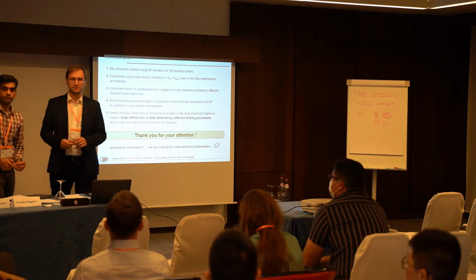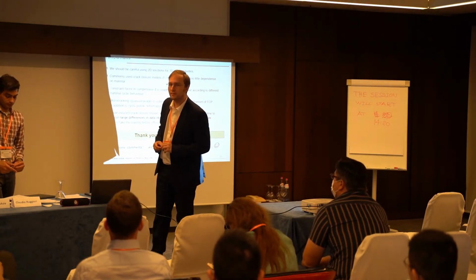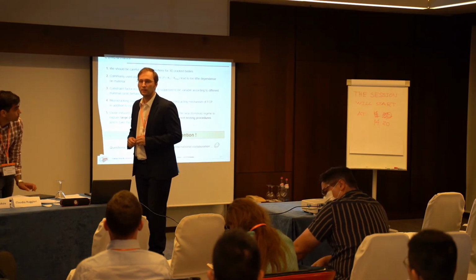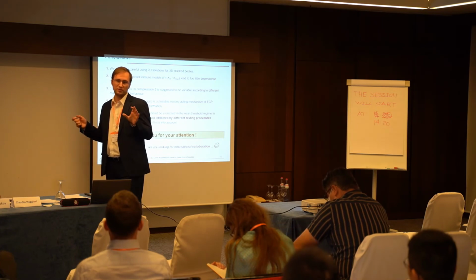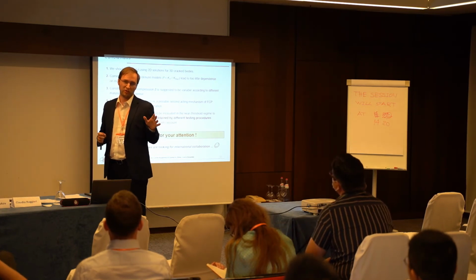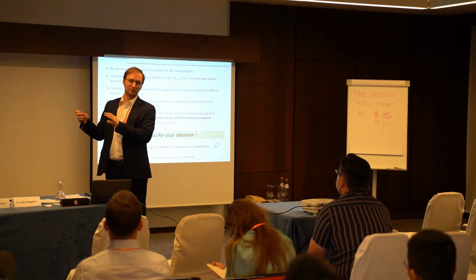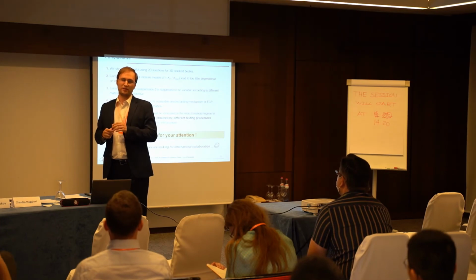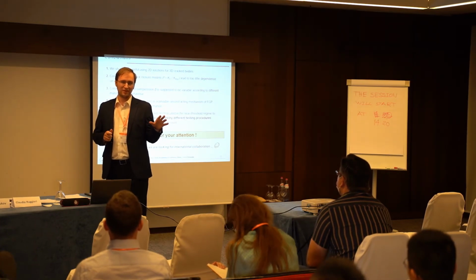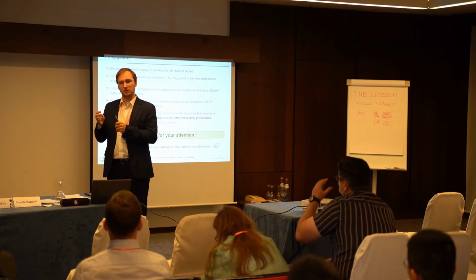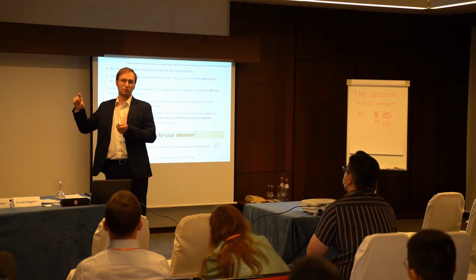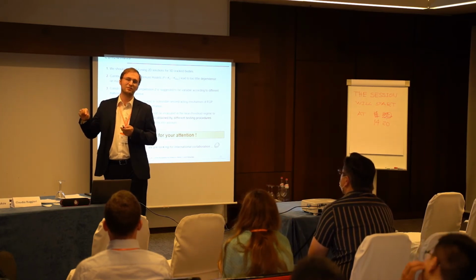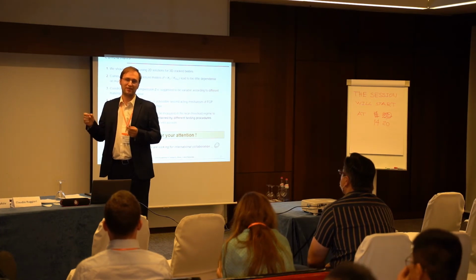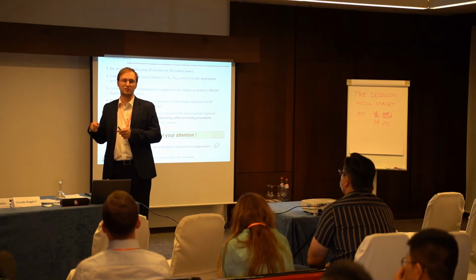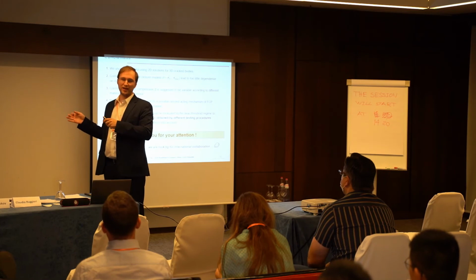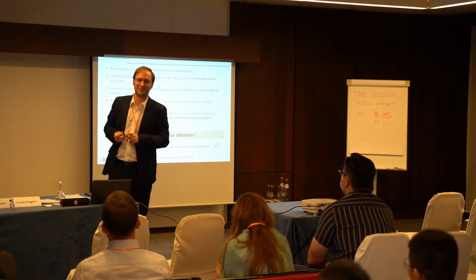So what happens if crack closure is not correct? If the theory of crack closure is not correct? What happens with your result? Yeah, one is plasticity-induced crack closure, one is oxide. In plasticity, there's much debate whether it's correct or not. What we know is there is a load ratio effect, and you may look at it as a crack closure concept, or you may look at it like, okay, we have delta K effective, which is smaller or larger, and we cannot be really sure whether crack closure is the mechanism causing this. So actually we may use the crack closure concept for describing the load ratio effect without being sure about the mechanism. If that satisfies your answer.